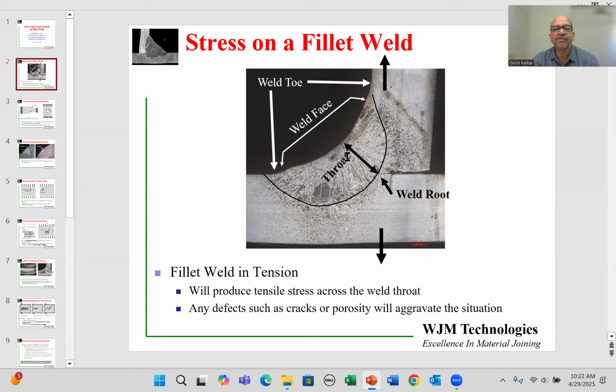Other important features of the fillet are the weld toes. The toes are where the front face of the fillet weld blends with the base metal. This is the weld face itself, and at the other side is the weld root. The weld root is the farthest point on the weld interface which has not been welded. So along this line of the weld interface, there is no weld, but the front edge of it has been welded. The throat is effectively the shortest distance from the weld root to the outside face.